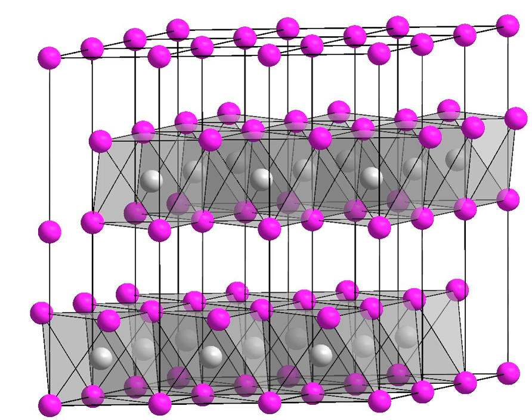Titanium disulfide nanotubes with open-ended tips are reported to store up to 2.5 weight% hydrogen at 25 C and 4 megapascals hydrogen gas pressure. Absorption and desorption rates are fast, which is attractive for hydrogen storage. The hydrogen atoms are postulated to bind to sulfur.